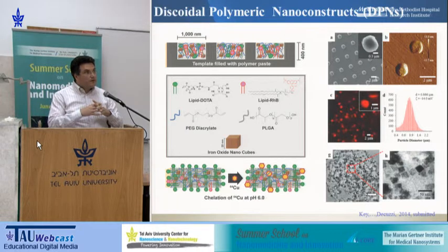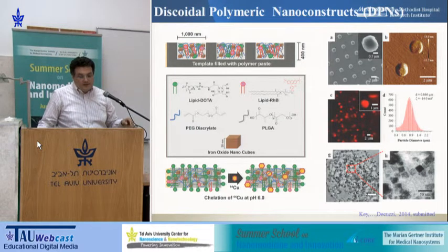And they are forming a very complex matrix which is still very porous, and now has domains that are hydrophobic, domains that are hydrophilic, and then you have these lipids that have their own functionalities. This lipid here, we use it for fluorescent, for optical imaging. This lipid here, lipid DOTA, we use it for MR imaging because the DOTA cage can be used to carry gadolinium ions. But we also use this for nuclear imaging because the DOTA cage can be used for carrying copper-64 ions.